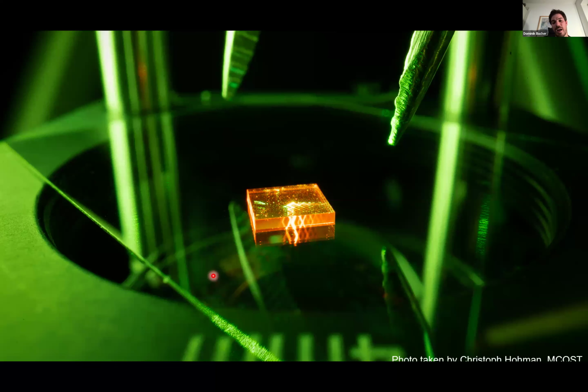Okay, so that's how it looks like in our lab. So I have to disappoint you. We don't work on nano diamonds. We have these millimeter-sized diamond chips. You see it in here. This is like a 2 by 2 millimeter diamond chip. This diamond is doped basically everywhere with NV centers. So you see here the laser going through, which is green, and now we just filtered the green light. So you see basically the red emission, which is the fluorescence emitted by the NV centers. And I told you before, the emission is spin state dependent, which we then will use to read out our quantum sensor.